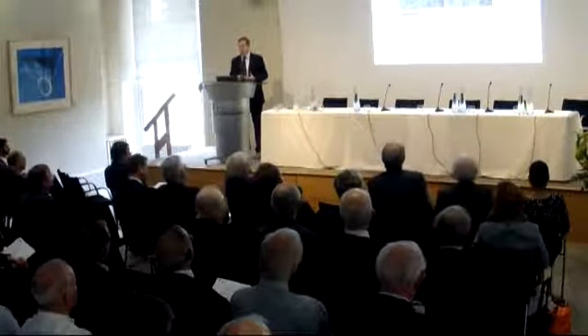If we extend these experiments over longer periods of time, we can look over 50 charge cycles, 100 charge cycles, 200 charge cycles. Again, crucially, this is a non-destructive technique, so we are empowered to do these four-dimensional studies in a completely non-invasive fashion. We can begin to image the effects of aging, and again, we've identified pore widening effects, hoop cracking effects, and so forth.